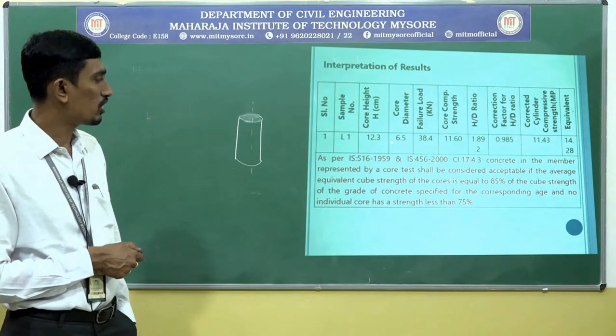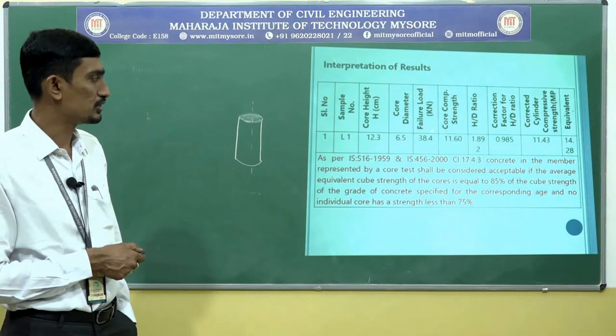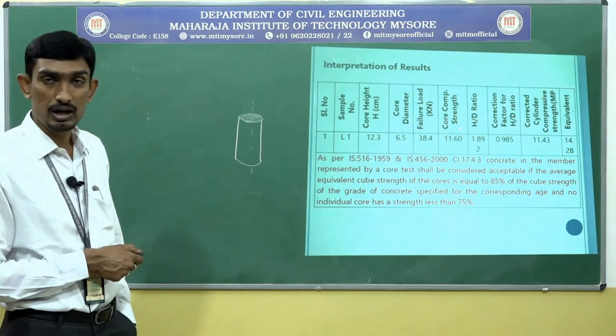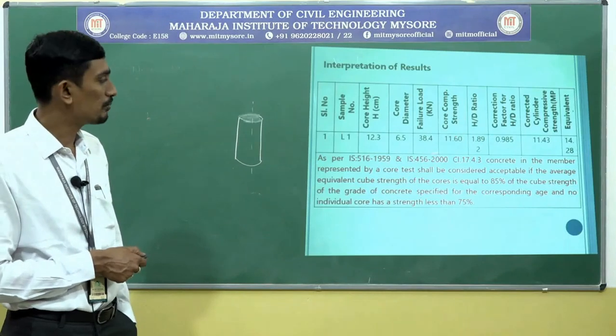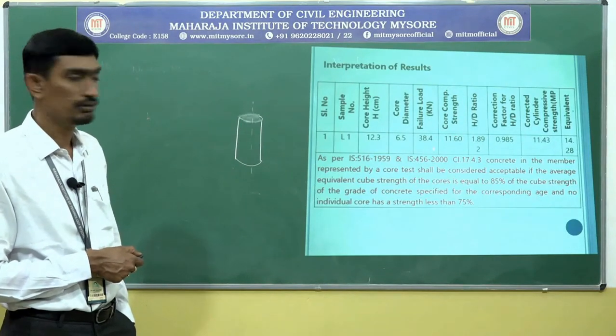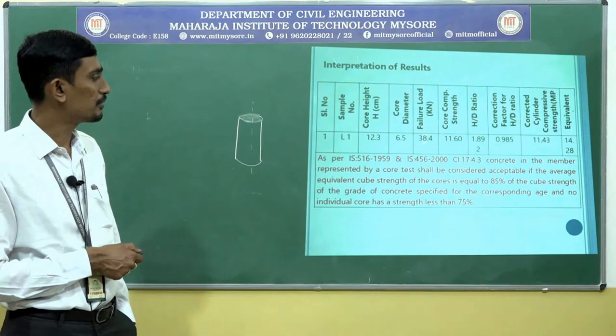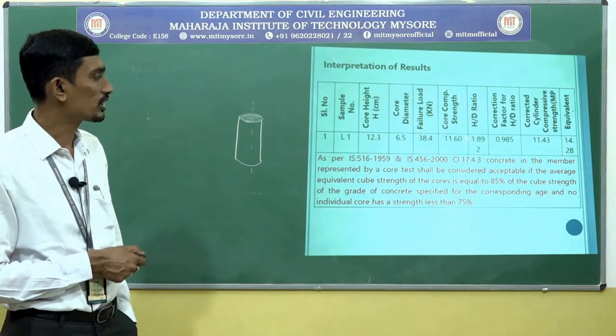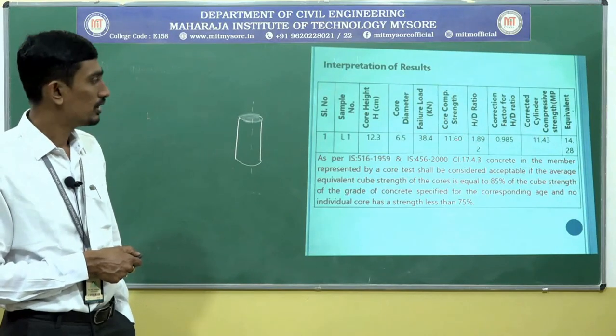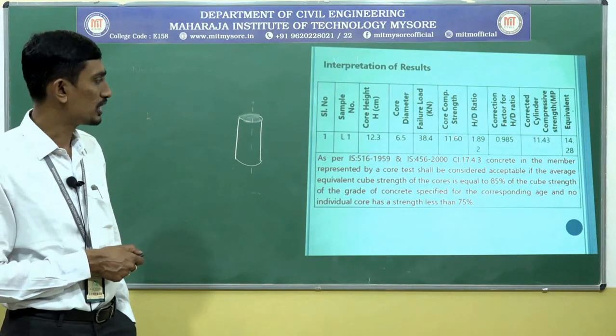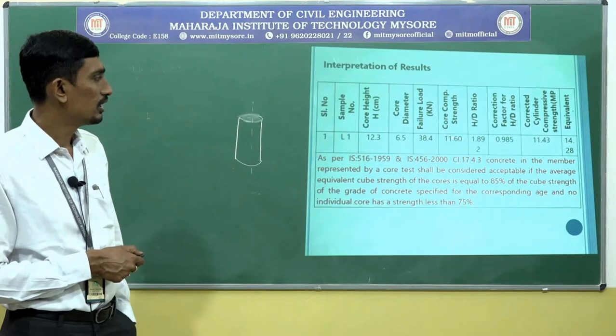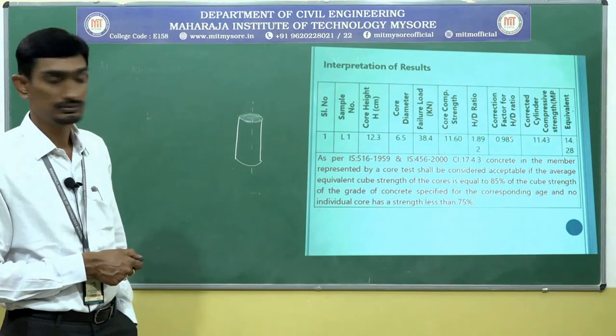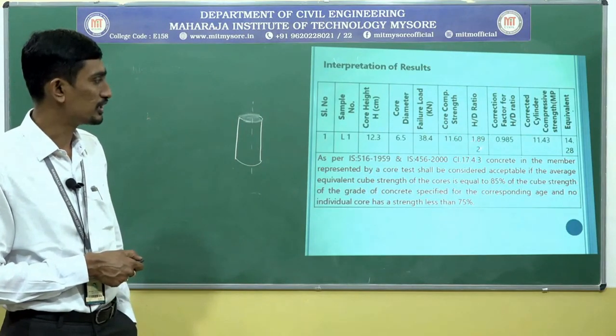Next, to this concrete core specimen, apply the compressive load. After applying the compressive load, you got a breaking load or failure load of 38.4. For that 38.4, you know the H and D, so calculate the core compressive strength. For the calculated core compressive strength, you multiply with this correction factor. This is the correction factor based upon the H by D ratio.